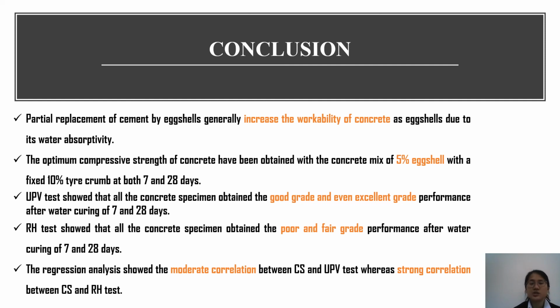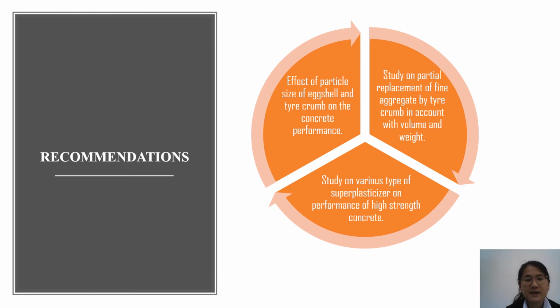Lastly, the regression analysis showed the moderate correlation between compressive strength and UPV test, but the strong correlation between compressive strength and rebound hammer test. Last but not least, here are my recommendations for future researchers on this relevant topic. First, the effect of particle size of eggshell and tyre crumb on the concrete performance. Secondly, study on partial replacement of fine aggregate by tyre crumb in terms of volume and weight. Thirdly, study on various types of superplasticizers on performance of high-strength concrete.